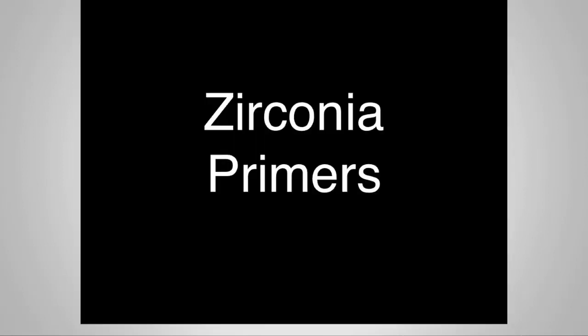Primers. Do you need zirconia primers? Well, that's a good question. With some products you do, with some products you don't. Zirconia primers can increase your bond to the zirconia from your resin cement. And like I said, other products like the SpeedCEM Plus, with SpeedCEM Plus, you can just use the Ivoclean, and then go straight to your SpeedCEM Plus. You're going to get really good adhesion to the intaglio surface of the crown with the SpeedCEM Plus.